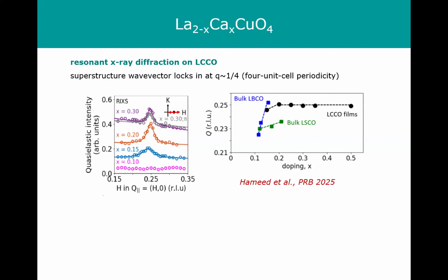Anyway, what recently happened in the group is that Sajna applied the resonant X-ray scattering technique to look for charge order, as this Chinese group did in their lanthanum strontium copper oxide crystals. And she found these resonant peaks over a wide range of doping levels. Basically, at every doping she looked, she found resonant peaks. At very low doping level, they followed what is known from bulk 214 systems. So, they're incommensurate and move with doping. But then at about doping level 0.2, just about optimum doping or so, the periodicity locks in to 1/4. So that means 4 unit cell periodicity.